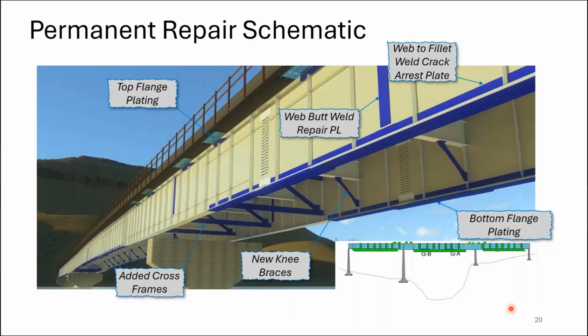We had a web butt weld repair plate. So this basically addressed any indications that were in that full height weld between sections. We had the web to fillet weld crack arrest plate, which Francisco will get into some details, and then some continuous bottom flange plating in all the tension areas in the 3 main spans.